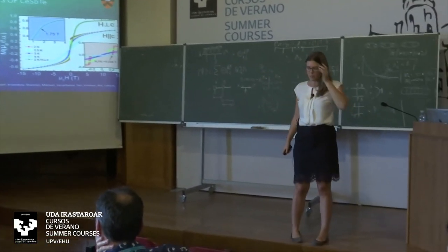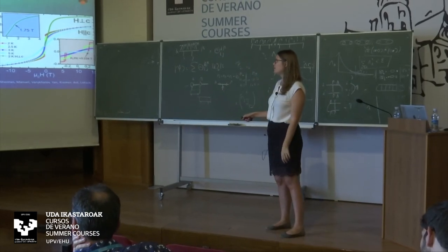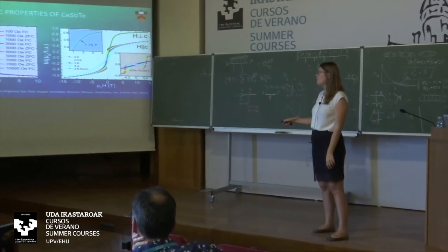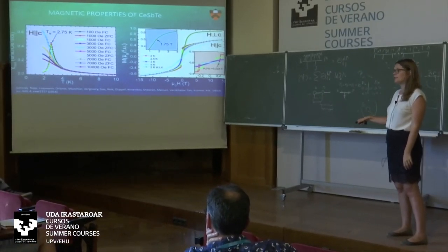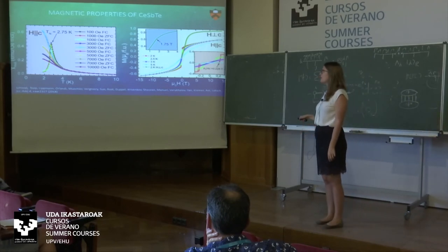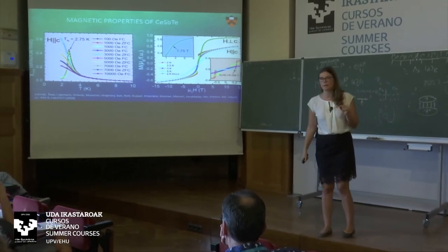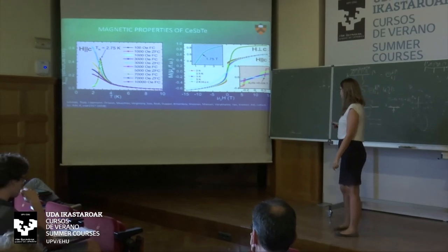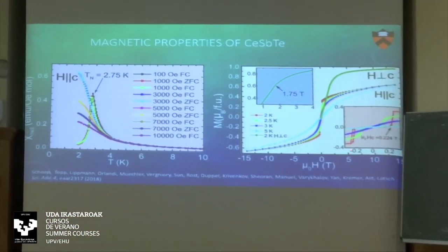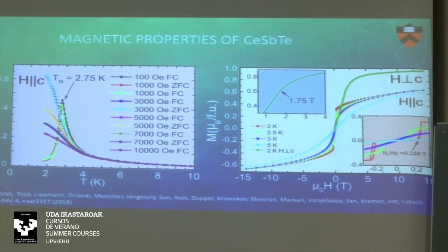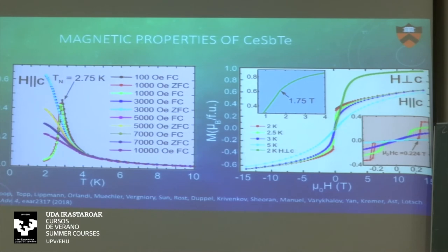The band structure without magnetism — ignoring f-states, putting them in the core — was calculated by Maya. We do have a non-symmorphic touching point at the Fermi level, a gapped line node gapped a bit higher now because spin-orbit coupling gaps it, and another tilted Dirac crossing along the gamma-Z line. ARPES confirmed the band structure roughly looks as predicted, matching the surface-terminated band structure pretty well. We then checked the magnetic properties: measuring temperature-dependent susceptibility in a low applied field, we get a really nice cusp-like transition indicating an antiferromagnetic phase transition.